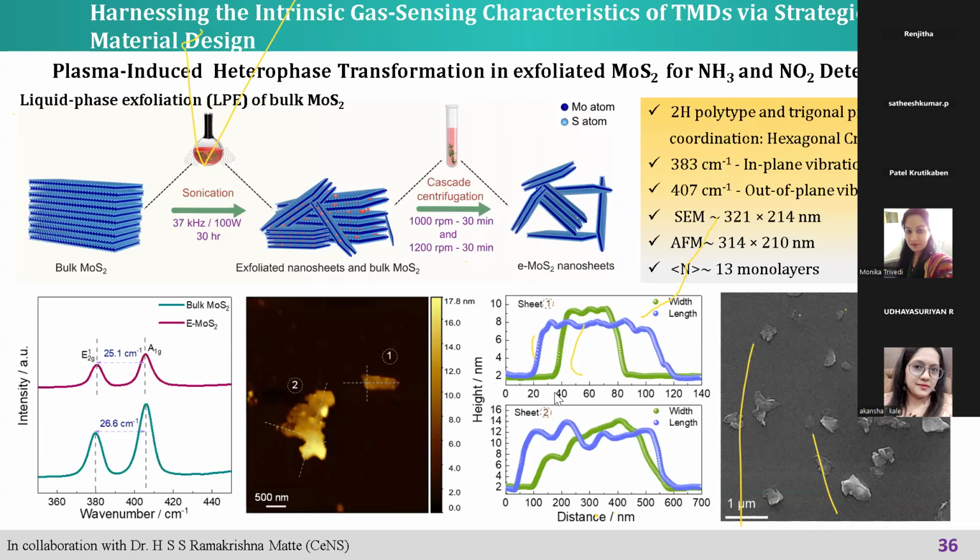These are the basic characterizations, how it is characterized. This is very interesting. They take this 2D material, put it on a substrate, and then use an atomic force microscope. An atomic force microscope is nothing but a sharp tip with atomic resolution, in the sub-nanometer range. The tip moves over the substrate and scans, and the tip movement gives the surface morphology. So when we have these layers of 2D material on top, the tip will just see how the layer is there.